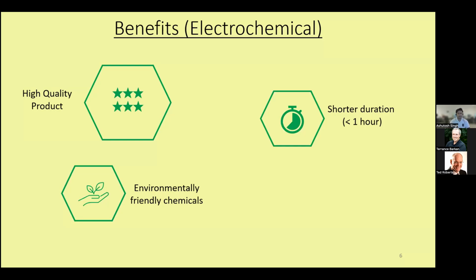Another advantage is that we usually control these experiments, and they take less than an hour to completely consume the graphite in the reaction. In all of the chemistries that we developed, we used environmentally friendly chemicals. So we don't have any hazardous solution that requires huge safety detailing, or an issue of disposing of hazardous chemicals. We usually use environmentally friendly chemicals.